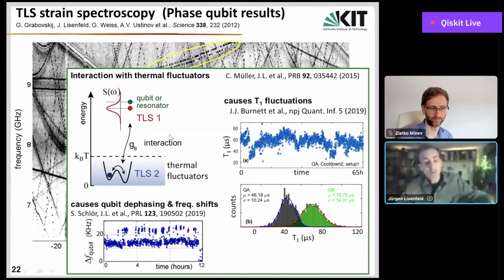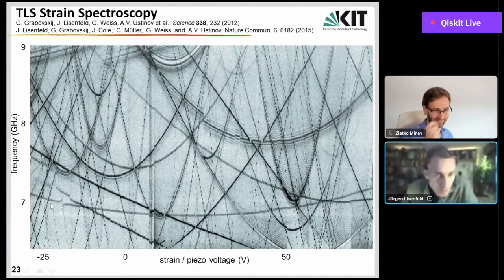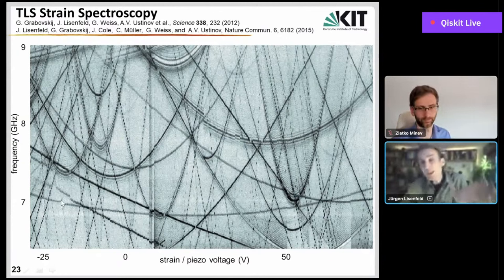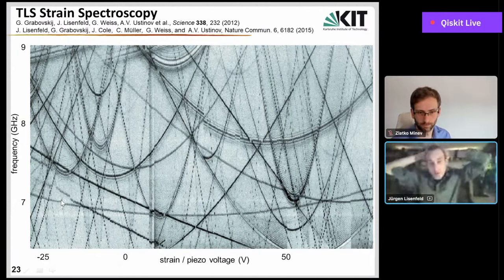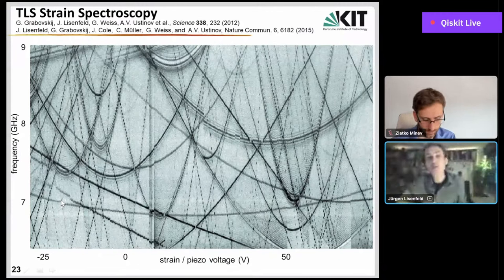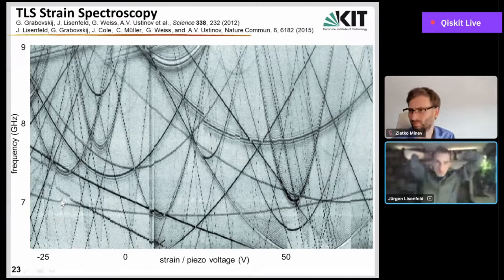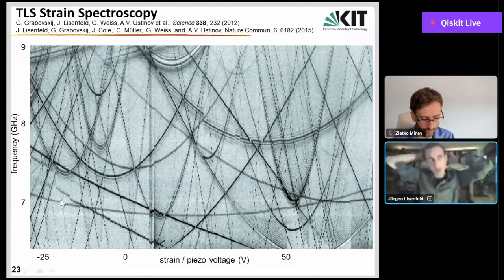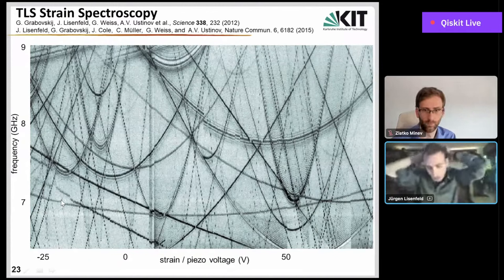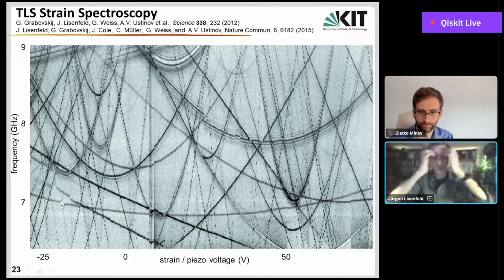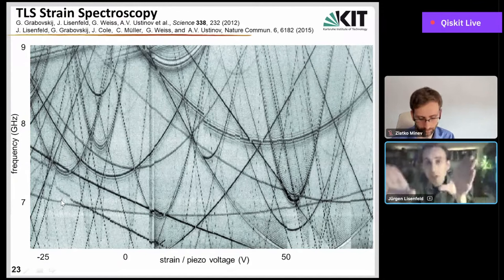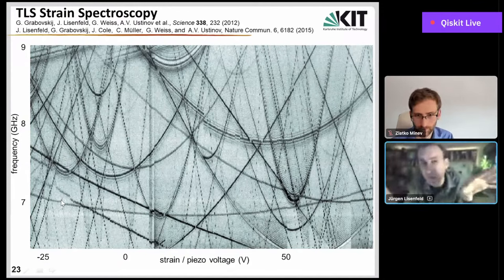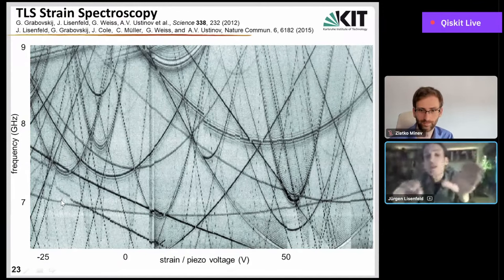Here's just another data set showing, again, some avoided level crossing. The nice thing on these measurements was that you could just warm up your chip and cool it down again to see a completely new spectrum, which I think is mostly due to the fact that you would just look into a different strain window. When you warm up and cool down, you have, of course, thermal dilatation of everything, and this is all very sensitive to strain. So I'm not saying that when you warm up, all atoms rearrange into new defects. Most likely you just look in a different window, and that's why you find different defects there.